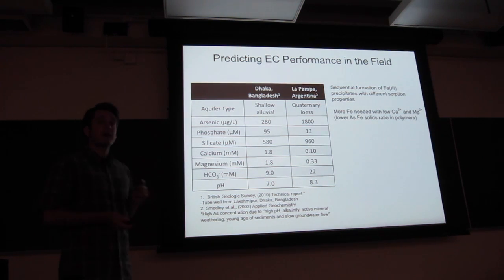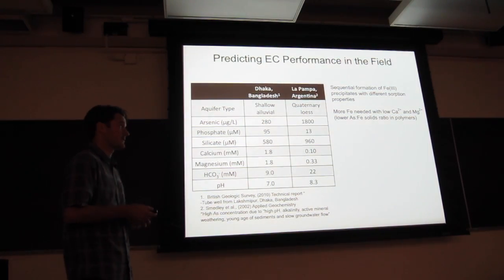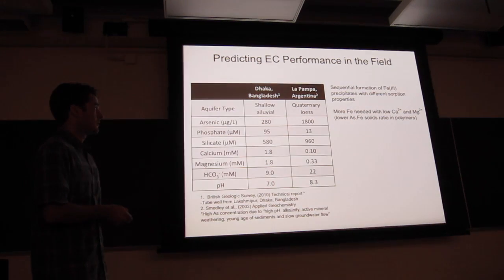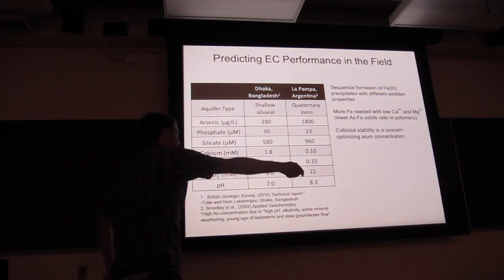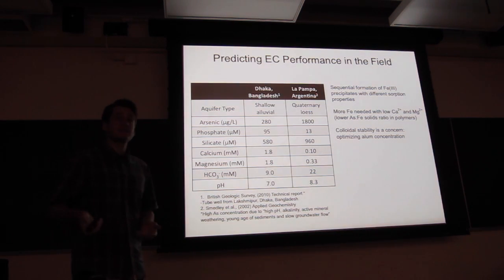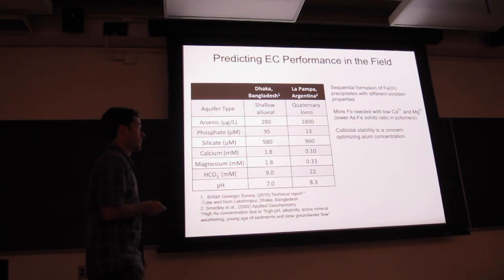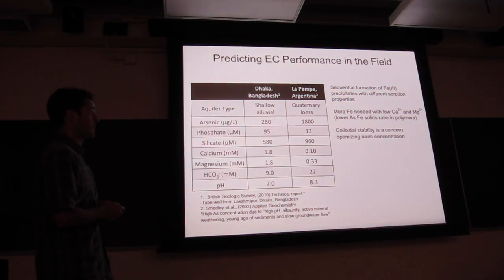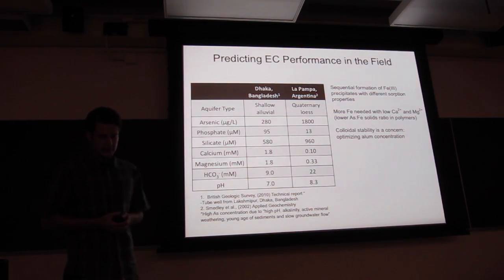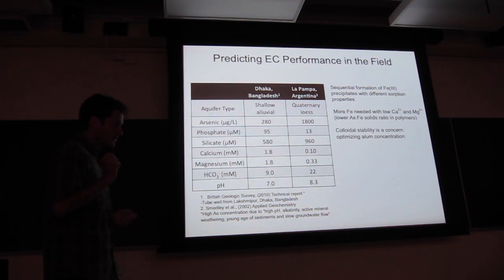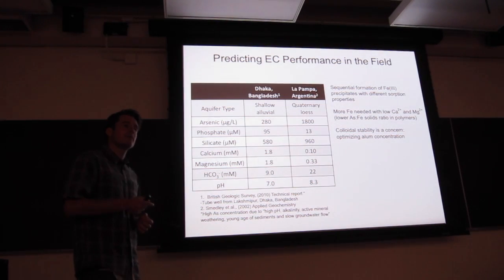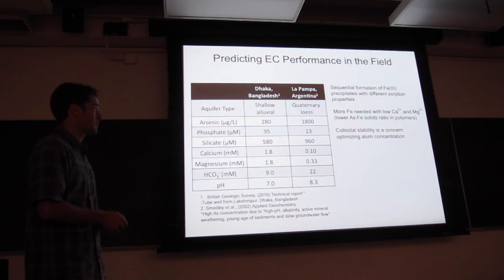But in the case with low calcium and magnesium, we're going to have to generate much more iron because the sorption capacity of these polymeric iron oxyhydroxides is going to be lower in the absence of calcium and magnesium. Colloidal stability is going to be a problem. For example, in this groundwater from Argentina with a low calcium and magnesium concentration, we're going to have to do a little bit of work to optimize the amount of alum that we're adding to aggregate the particles.